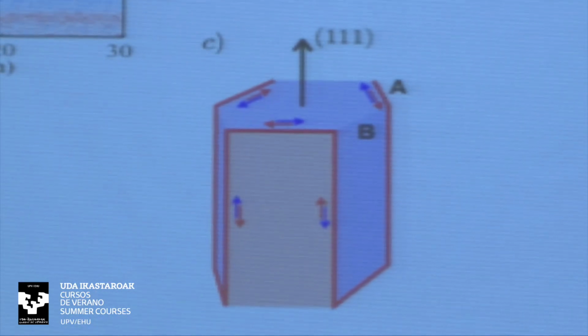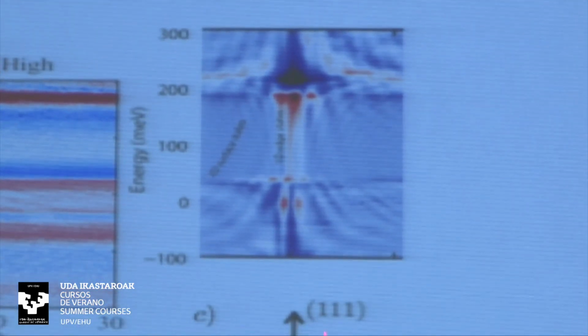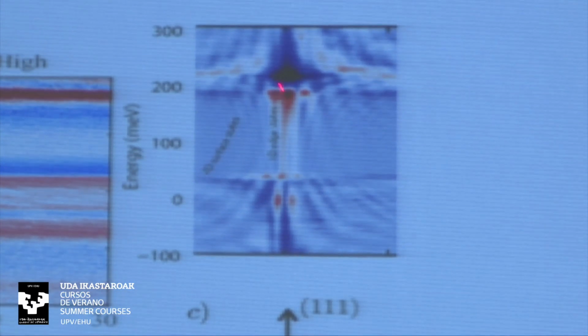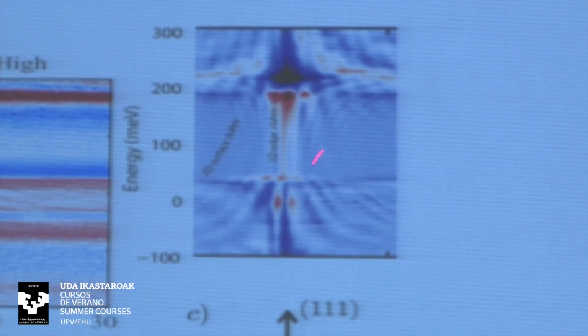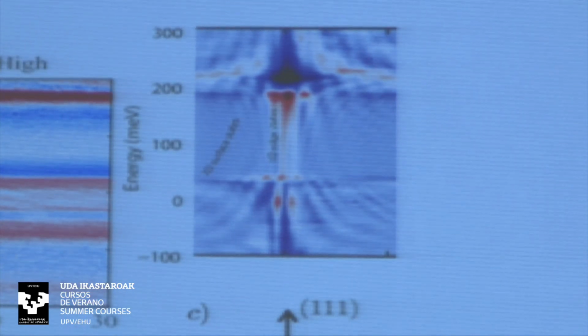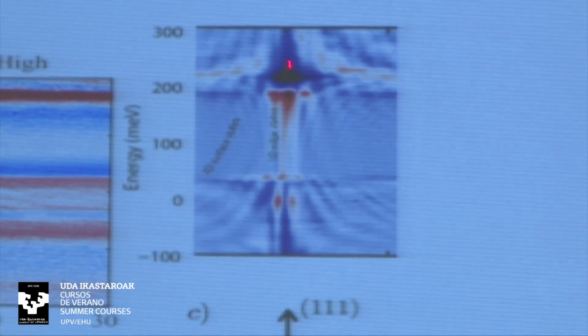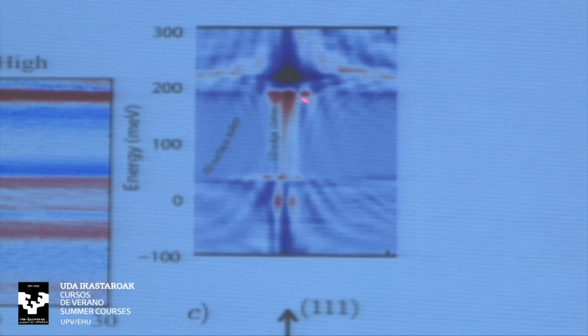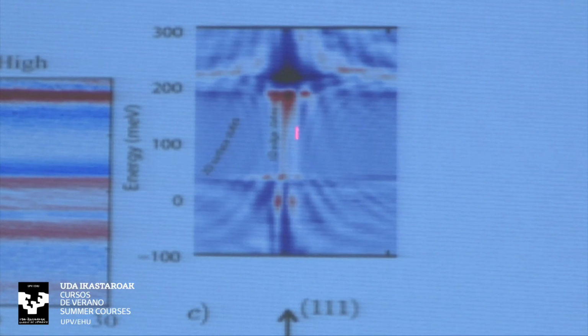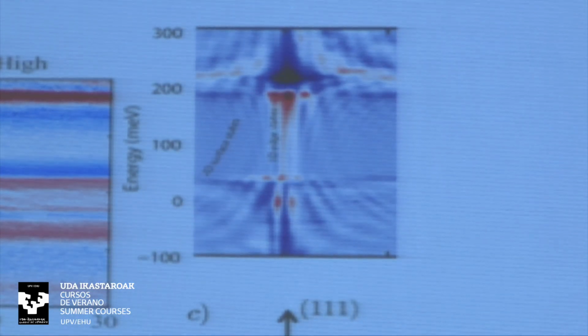And this is how it evolves in energy. So here there's a step edge. This is still data from Princeton. You can see, beyond all this dispersing pattern that we've seen also before, and here it is again in our data, there's also some part which doesn't disperse. This is this red line, a non-dispersing line that really sticks to the step edge.